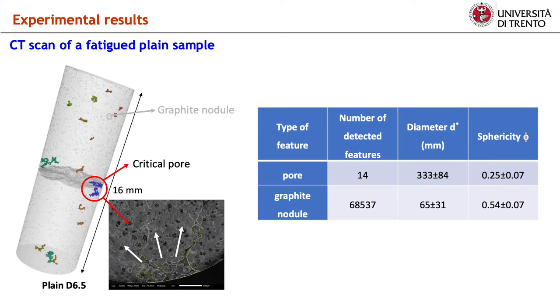CT scans performed on plain samples provide a convincing interpretative key of the above described fracture scenario. In this CT data image of a fatigue plain specimen, shrinkage microporosity is highlighted in a color scale expressing the pore volume.